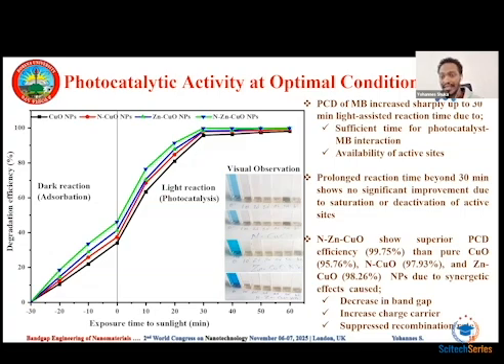The photocatalytic degradation of methylene blue increased sharply up to 30 minutes of the reaction, which indicates sufficient time for interaction of methylene blue with the material and availability of the active sites on the surface of the material. For longer reaction times there is no significant change. This indicates the saturation of the active sites. The increased efficiency is caused by the increase in active sites, increased charge carriers, and the suppression of recombination, which results in the maximum degradation efficiency for nitrogen zinc copper oxide compared with the single doped and the pure copper oxide nanoparticles.